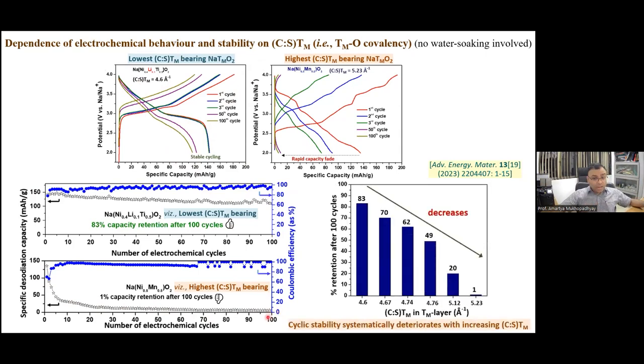And why is it so? We can see that with systematic variation in the charge to size ratio, as the charge to size ratio increases, that is, as the covalency of the transition metal oxygen bond increases, we see a decrease in the electrochemical cyclic stability. This again proves that if one wants to use a layered transition metal oxide in a real sodium ion cell, then the materials should have at most these charge to size ratios in the transition metal slab. But why does the charge to size ratio in the transition metal slab impact the cyclic stability, which has no relevance to water soaking, because these materials were well protected?